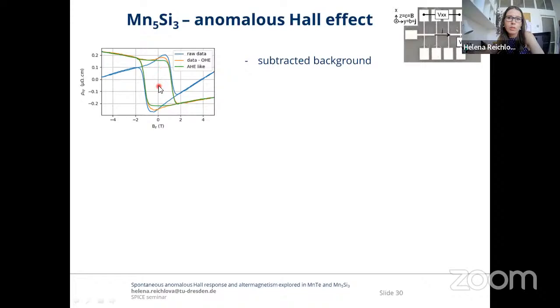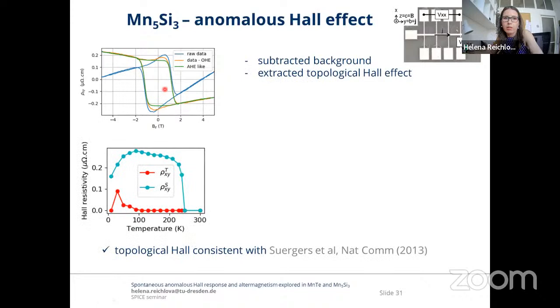non-collinear order. When we extract this topological contribution and plot it against temperature, we see that it's present in the low temperature magnetic phase. It has a magnitude very consistent with Suergers' data, and it's completely absent in the high temperature magnetic phase. This is in clear contrast to the anomalous Hall part, which is present almost unchanged in the full temperature range, and it only disappears in the room temperature paramagnetic phase.